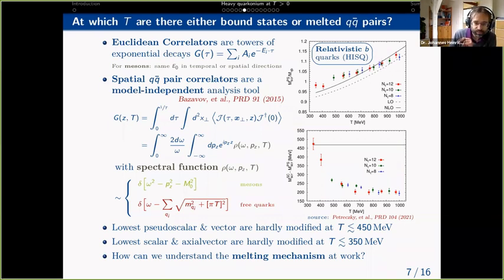Here in this plot, we look at the mass difference between the scalar meson and the pseudoscalar meson in this sector. What you see at the horizontal line is the zero temperature value of the difference, and you see again at 350 MeV, the difference is within uncertainties consistent with the zero temperature result. Then there is a rapid drop over the next couple hundred MeV of temperature, and then it slowly keeps decreasing. This rapid drop indicates the state is melting, and this slow decrease after that is sort of a suppression of the finite temperature effects by the large masses of quarks.